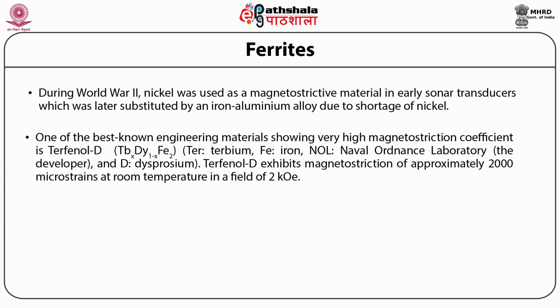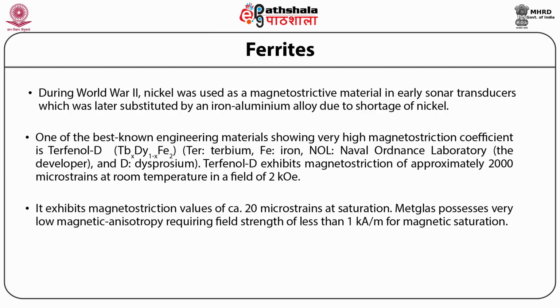Another common magnetostrictive composite is an amorphous alloy of iron, silicon, boron, and carbon with a chemical formula of Fe81Si3.5B13.5C2. This is also known by the trade name Metglas 2605SC. It exhibits a magnetostriction value of 20 microstrains at saturation. Metglas possesses very low magnetic anisotropy, requiring a field strength of less than 1 kiloampere per meter for magnetic saturation.